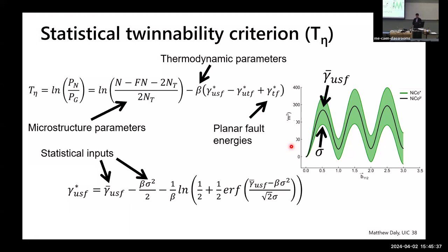So this is what this term is capturing here, how the microstructure is being chopped up by the presence of twins. And the second part is similar to what we saw in the previous twinning criterion, at least in a certain sense, the energetic penalties associated with twinning or slip. And what we've added and overlaid on top of this is the statistical noise. So the statistical noise, meaning how we should adapt these barriers, this comes from some expected value analysis that we have, where we are modifying the average value by adding in information about the standard deviation. And what you'll see importantly is that if the standard deviation goes to zero, you recover the average barriers, which is what you should expect. So that's the,